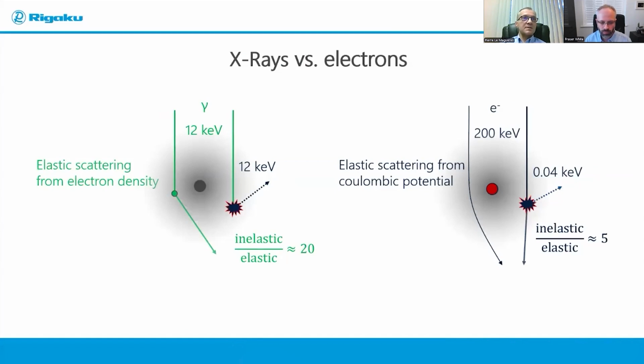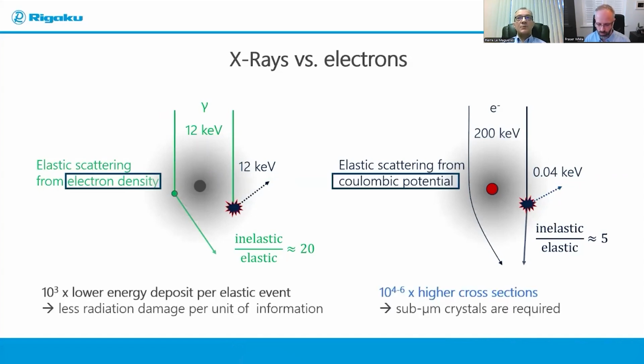On the left-hand side, you see that X-ray photons are being diffracted by the electron density around the nucleus of atoms. Whereas on the right-hand side, an electron beam is diffracted by the Coulombic potential around the nucleus of these atoms. And as a result, the interaction of an electron beam with crystalline matter is much stronger than the interaction of X-ray photons with crystalline matter. It can be stronger by 4, 5, or even 6 orders of magnitude, depending on your crystal, the size, and so on and so forth. So this is a huge gain in interactions when you move from an X-ray beam to an electron beam.